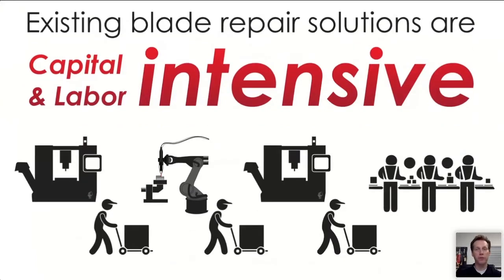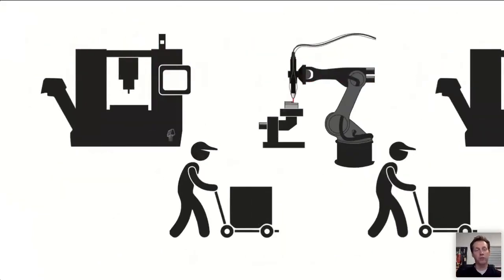If you're not familiar with repairing blades, it is a very intensive process. It requires a significant amount of capital and expertise, skilled labor to be able to do it. And pictographically along the bottom of this image, we've tried to show some of the general steps. Typically, the first step is a grinding step. It can happen in a milling machine or, well, a tip crop often is what it's called, but it's a removal step. It can be with a manual grinder or with a machine tool. You remove the worn or decayed material.